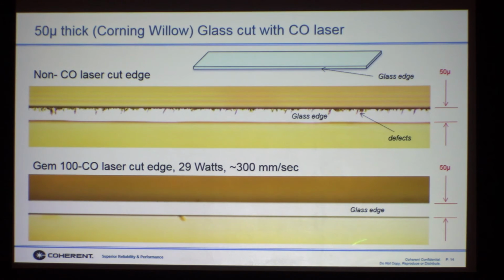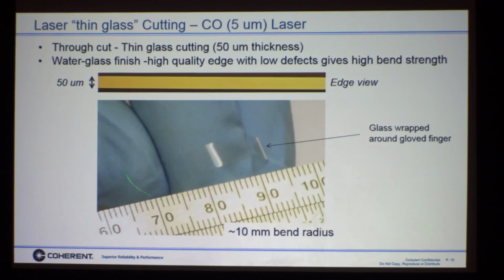Below is a piece that we cut with the CO laser, okay? We used 29 watts, focused circular beam, no cooling jet was necessary, and we have a perfectly clean edge in this case. And what a perfectly clean edge does in thin glass, this isn't strengthened, it's thin glass, it gives you the strength. There are no defects. So this particular piece, we would pick up and bend slightly and it would crack. And the cracks, of course, all start at these defects, okay? The piece that was cut on both sides with the CO laser, you could wrap several times around your finger.